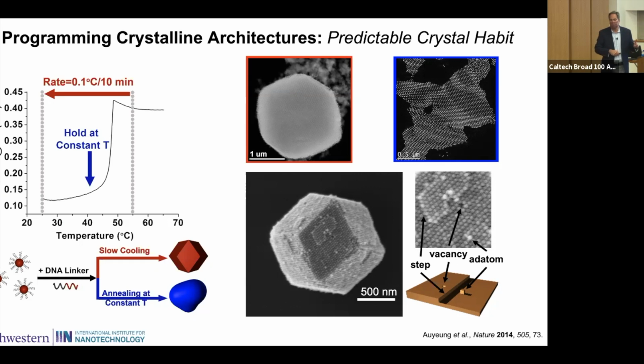The reason is very simple. That is the Wulff construction. That is the thermodynamic sink. That experiment was critical. We published that in Nature because that not only validated that you could get single crystals for the first time, but it validated this concept of the complementary contact model. Now, the complementary contact model is not a law. It's just a rule. And it works greater than 90% of the time, at least in our hands, of all the different types of structures.